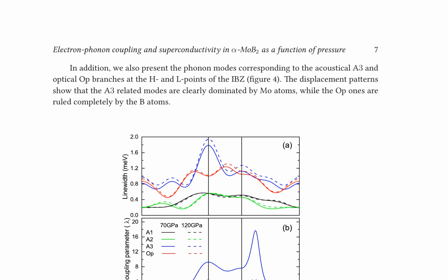superconductors. Electron-phonon coupling and superconductivity in alpha MoB2 are investigated as a function of pressure. Phonon modes corresponding to the acoustic A3 and optical OP branches at the H and L points of the irreducible Brillouin zone, IBZ, are presented, revealing that A3-related modes are dominated by Mo atoms, while OP modes are ruled by B atoms. Linewidths and electron-phonon (EPH) coupling constants for alpha MoB2 at 70 gigapascals and 120 gigapascals along the AHLA paths are shown, highlighting the significant contributions of acoustic phonon branches, A1, A2, and A3, and the highest frequency optical